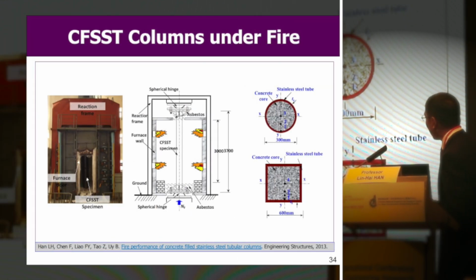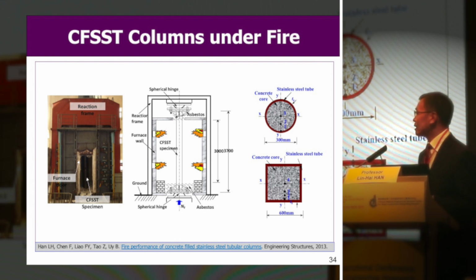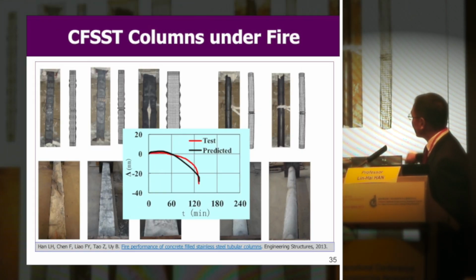Under fire, we have done some tests from 300 millimeters to 600 millimeters. So actually it's very large, full scale tests. You can see after test, you can see very beautiful failure mode. It's an outward failure of the outer stainless steel tube. You can see the concrete keeps well even after failure of structures. We have developed a model to predict the structural behavior as well.